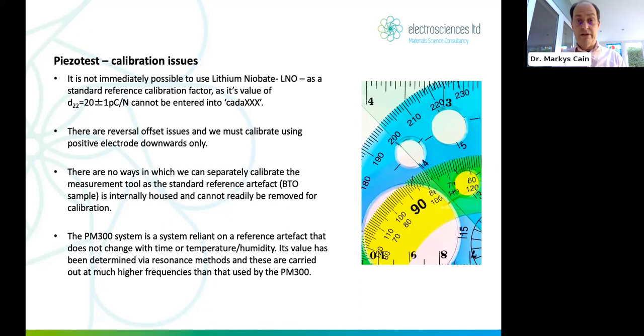They're single crystal, these materials. They are piezoelectric. Lithium niobate is also ferroelectric. Quartz is not, but it is piezoelectric. And the values of piezo coefficient are quite low. So the value of d33 in the case of lithium niobate is only 20, plus or minus 1 picocoulomb per Newton. Now, in the piezo test machine, you're not able to enter that as a reference value. You've got to have something over 100. I mean, it's just the nature of the way it's working. So there's various ways around this, and I'll go through that in a slide or two.